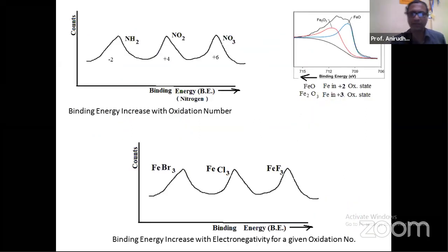Now, if you look at what is happening to these binding energies, I am going one step deeper. If you see this slide, at the top I have shown how the binding energies for nitrogen change depending upon the oxidation state of nitrogen. I've shown three different compounds: NH2, NO2, NO3. In NH2 the oxidation state for nitrogen is -2, while it is +4 in NO2 and +6 in NO3. If you see the binding energy for nitrogen in these environments, the core shell binding energy for nitrogen is the largest for NO3, at an oxidation state of +6, as compared to NO2, where the oxidation state for nitrogen is +4.